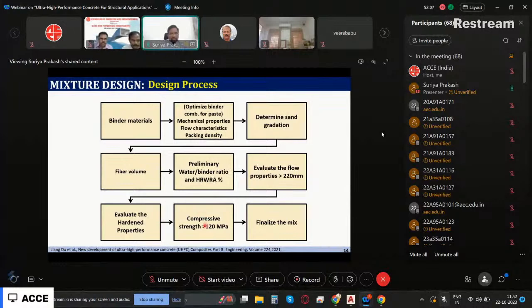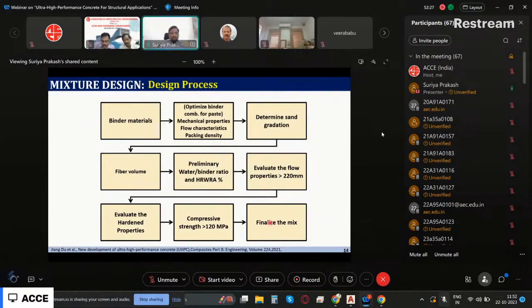The hardened property for UHPC is that it should have at least 120 megapascal. Now, if you're designing for 200 megapascal, then obviously you have to do the optimization again. Then finally, if the strength is as per your requirement, and your flow is as per your requirement, then we can go ahead and finalize the mix design. So this is the procedure that is given here, and this is what we do.